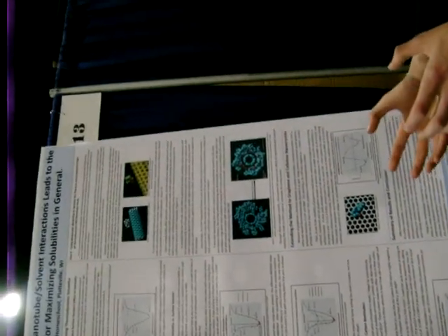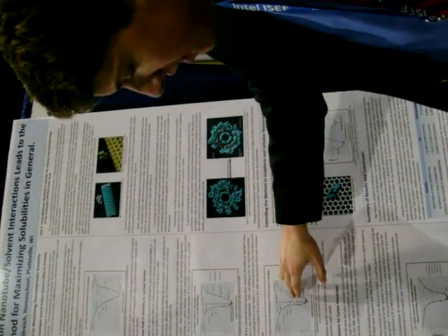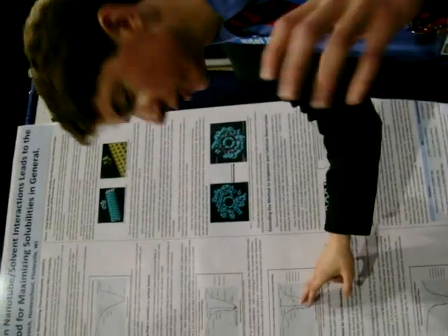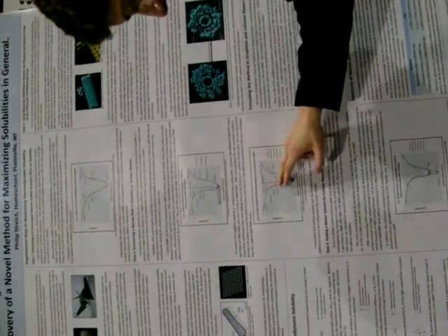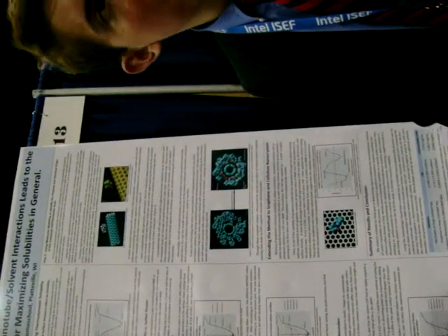So, to try to verify this peak, I mixed different solvent combinations. And when I plotted chi versus surface tension, these new peaks appeared, which were centered around the exact same surface tension, but had various depths. And so then, to try to understand what controlled how deep the peak went, I decided to calculate this chi for a series of slightly different pyrrolidone solvents.